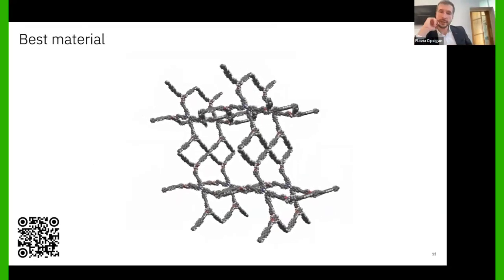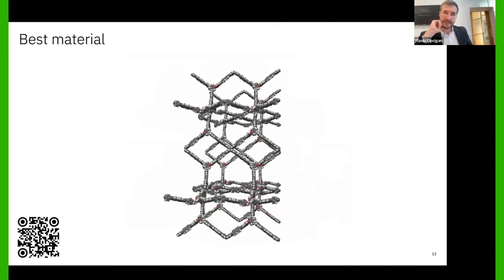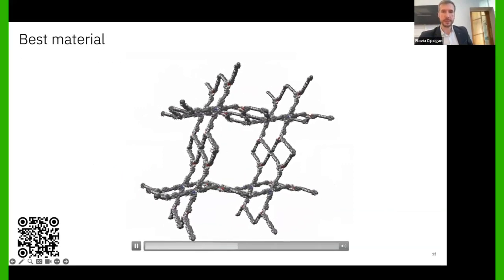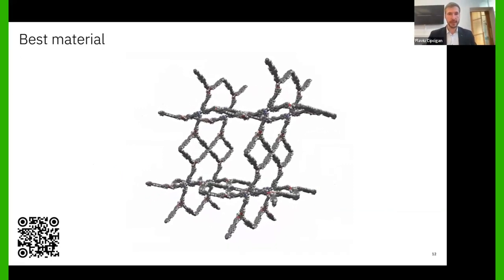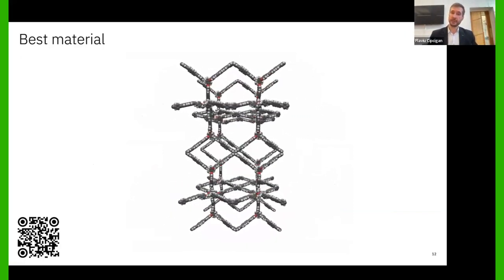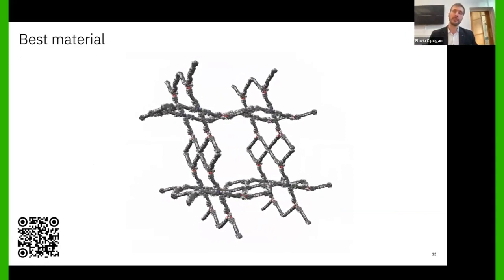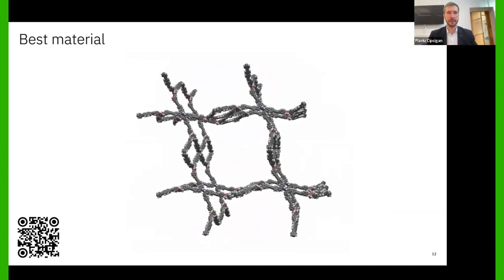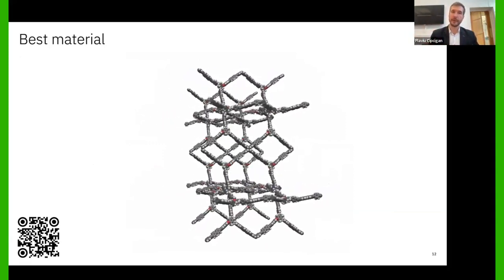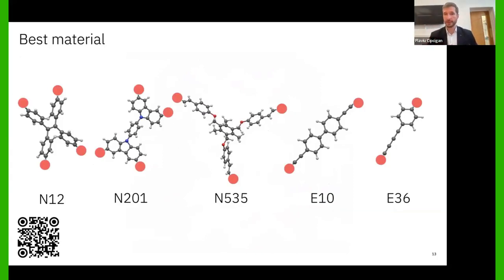Finally, this is a render of the best material in the data set that shows a pore size in the middle of about 87 angstroms and a gravimetric surface area of about 10,000 square meters per gram, as compared to around 5,000 of some of the materials that are in the reference data set. These are some of the building blocks. This is actually technically a covalent organic framework rather than a metal organic framework, since all of the building blocks here, so we have two square building blocks, we have a triangular building block, and we have two linkers. All of these are organic molecules rather than molecules which have metal atoms.